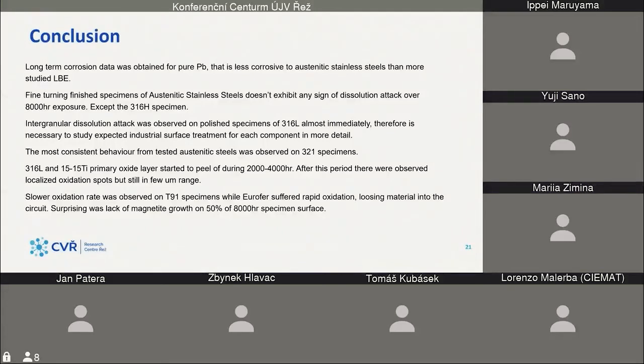We can draw some conclusions. Liquid lead is less corrosive to austenitic steels than the lead-bismuth alloy that is usually studied. Some of our fine-turned specimens of austenitic steel, except 316H, haven't shown any sign of dissolution attack of nickel over 8,000 hours. We observe intergranular dissolution attack on polished specimens even from 1,000 hours. So I think it's necessary to study the surface treatment expected in industrial processes for each component.